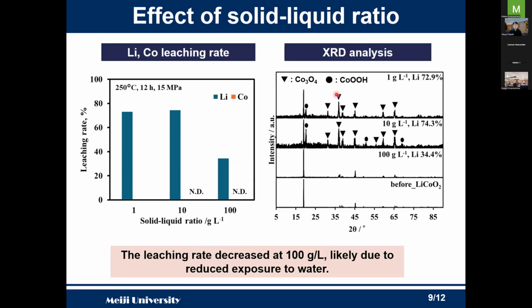XRD analysis shows that at 100 grams per liter, the LiCoO2 reagent was remaining like this. It is due to the reduced exposure to water, so much LiCoO2 did not react with the acid.